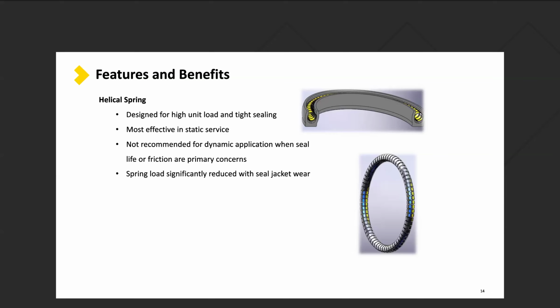We don't recommend it for dynamic applications. The high force, as a result, causes the seal jackets to wear very, very quickly in dynamic service. Now, we have used them. We've used them with materials like UHMW, and in a dynamic application, that's a very, very good wear material. So we have used this spring for tight sealing, low pressure in dynamic, but in general, we would say it's reserved for very slow dynamic or static applications. And yeah, the spring load significantly reduces as that seal jacket wears as a result.